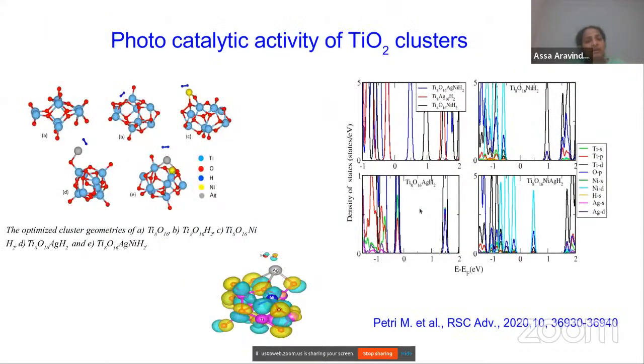Now, this is another example in which we have used DFT to confirm some of our experimental results in our lab. TiO2 clusters were synthesized, and they showed enhanced photocatalytic activity with doping. So we did DFT calculations on some very stable TiO2 nanoclusters. It is seen that the presence of silver is very beneficial for the hydrogen evolution reaction, and it is also modifying the band gap. On the right hand side, the density of states is shown, and with the nickel and Ag dopants, there are band structure changes happening, and there is also charge density difference, charge transfer occurring. So that is enhancing the activity of the TiO2 clusters.